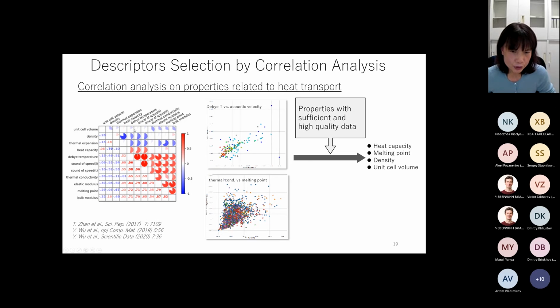Fortunately, these properties are not totally independent. In this graph, we show the correlations between these properties. We can see some properties do have a very high correlation, for example, the Debye temperature and the speed of sound, the acoustic velocity.